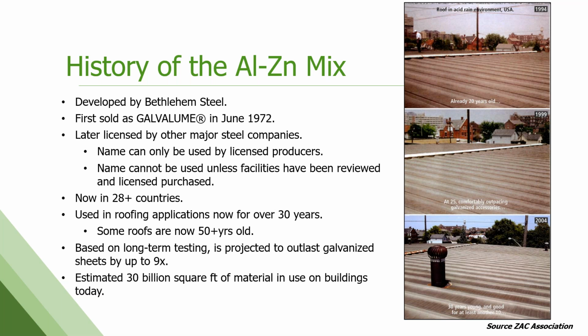And there's some pictures there on the right. This is a galvanized plus zinc aluminum roof in an acid rain environment. And what we're finding is that the Galvalume product outlasts galvanized by up to 9 times, and actually is outlasting the other building components used with it, right? So any galvanized components or components of other materials that are on a roof or a wall with the Galvalume product are failing first. So very long, great longevity. And we've got about, this is a little outdated now, it's probably more than this, but about over 30 billion square feet of material out in the market.